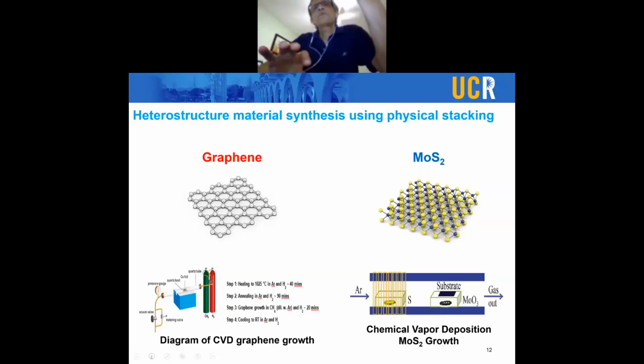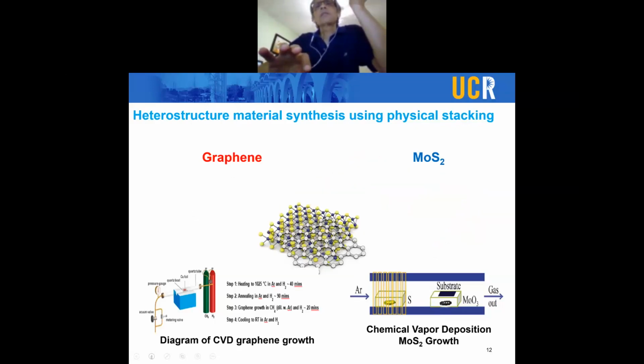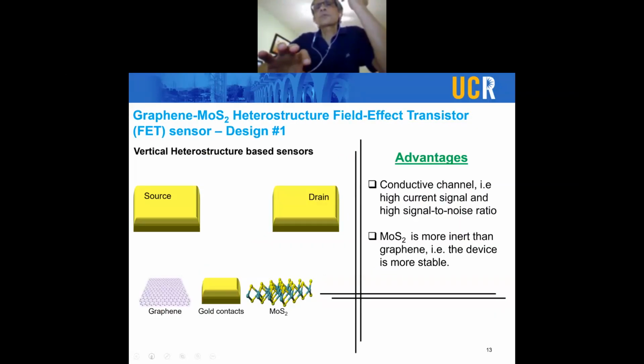We did the same. We use chemical vapor deposition of methane cracked onto a copper catalyst for the graphene. And for MoS2, we did CVD of molybdenum oxide and it reacted with sulfur vapors, and then deposited the vapors of MoS2 onto sapphire. And from sapphire, we lifted it off and created single layer sheets. And then we go ahead and stack them up to make structures. So there are two types of structures we investigated.